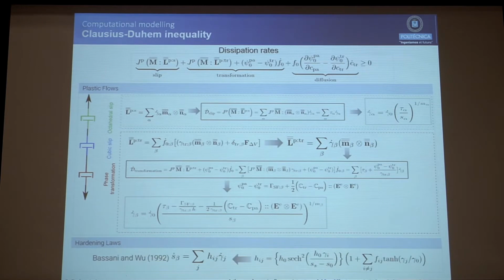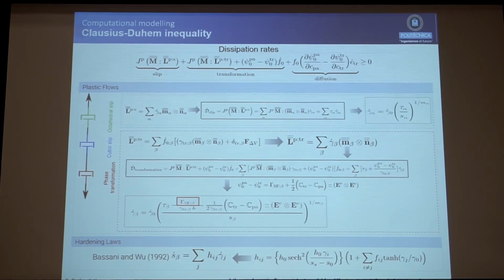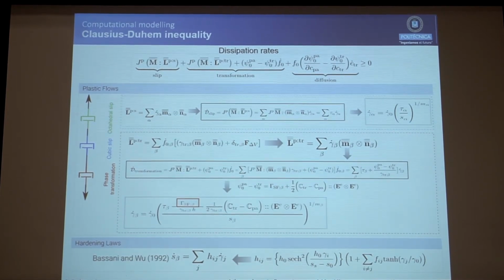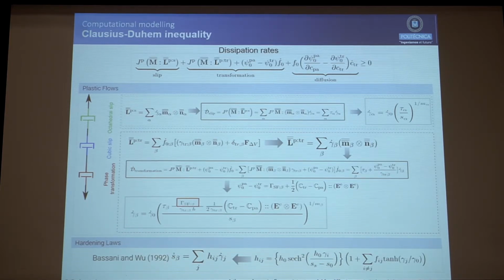And finally we have a standard hardening law, but the important part here is that this stacking fault energy depends on the chemistry, and it's changing during the whole plastic process, and it depends on how fast you are pulling the material, and at which temperature you are pulling, because the diffusivities and everything will change. So all the velocities of the chemical going to the plastic regions is going to change. So we need to solve the diffusion field at the same time as the plastic field if we want to include the chemical effects in this part.